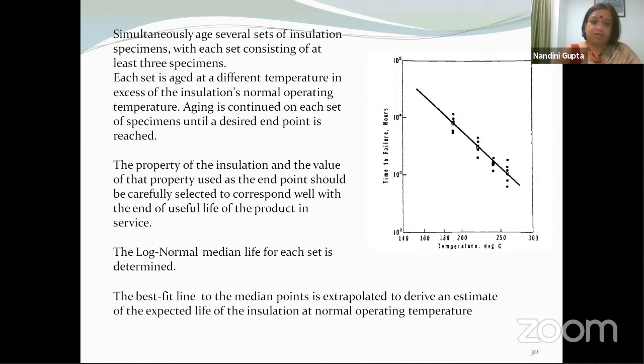You would first have to decide on the number of samples you would choose, and you would take several sets. And for each set, you would have to take a number of specimens. So maybe you would take each set consisting of at least 3 specimens. I say at least, the more specimens, the more reliable is your data, but at least 3 specimens have to be there. Each set is then aged at a different temperature. And these temperatures have to be in excess of the insulation's normal operating temperature, because we are doing an accelerated aging test. Aging is continued on each set of specimens until a desired endpoint is reached.